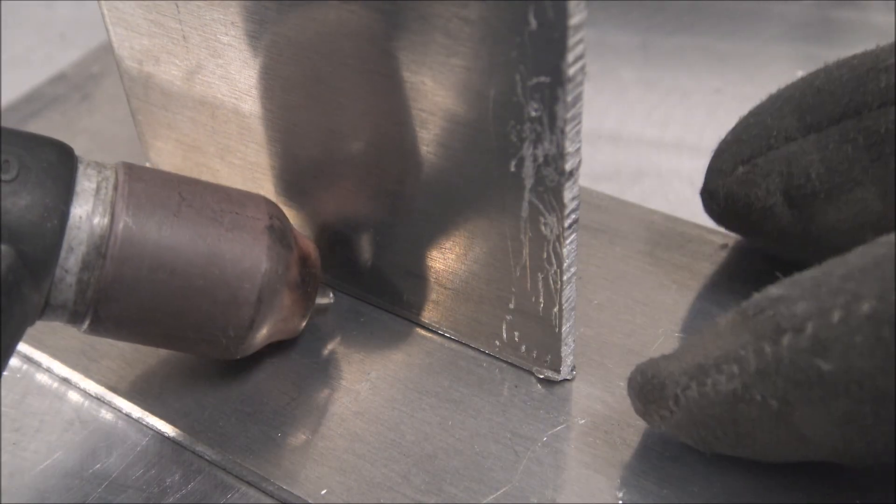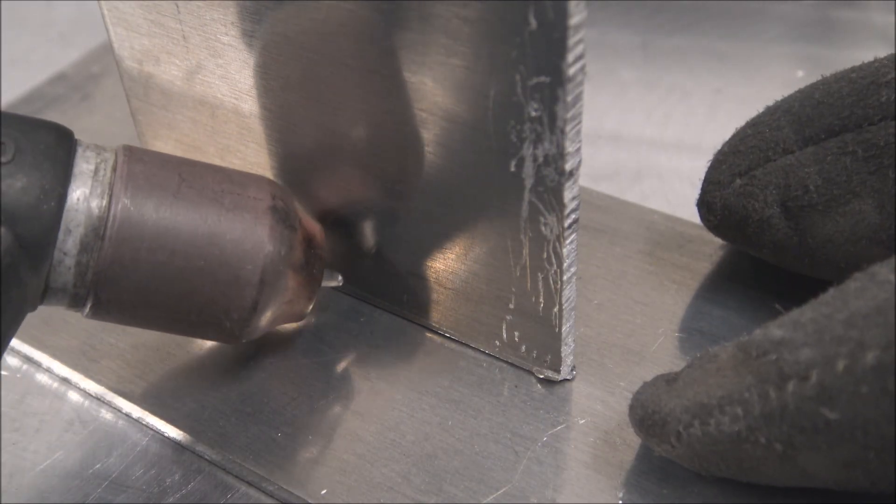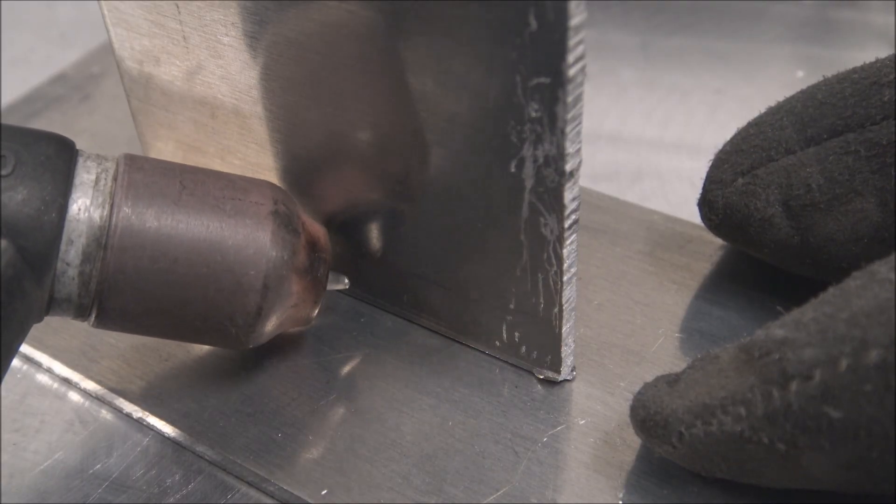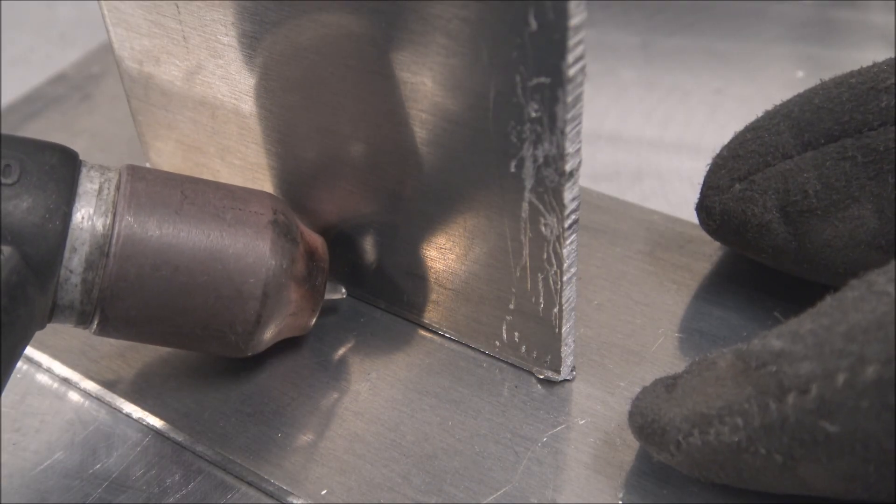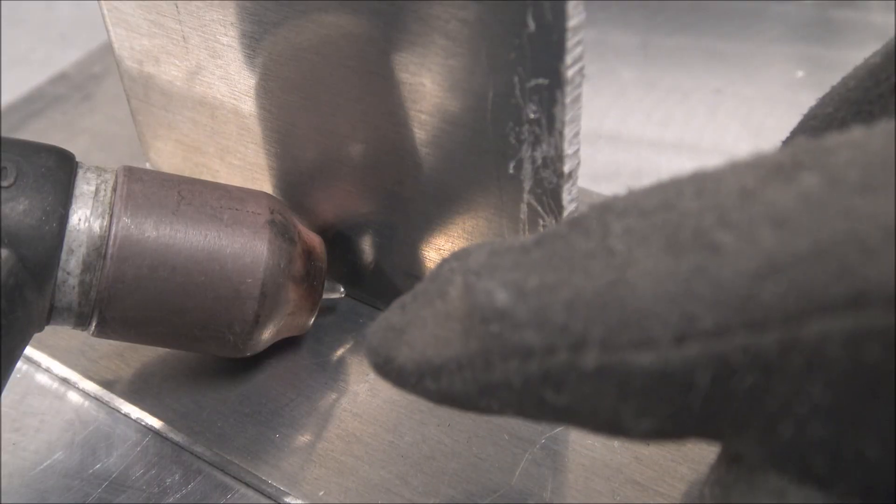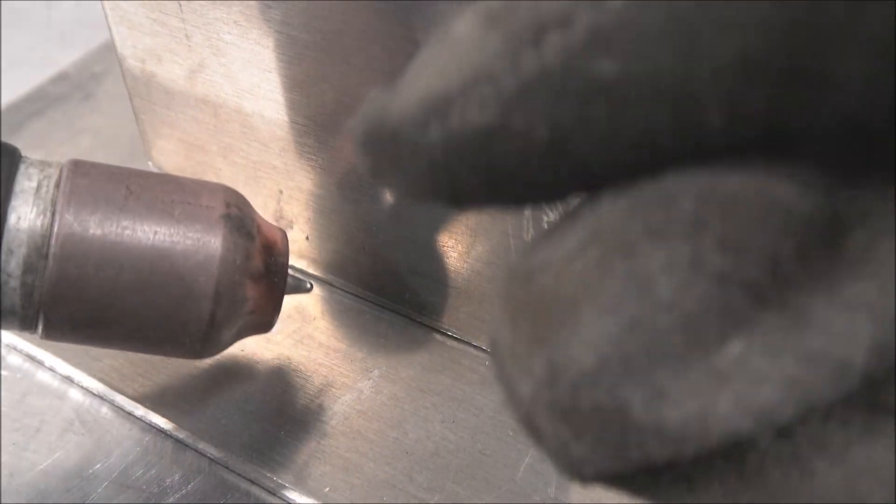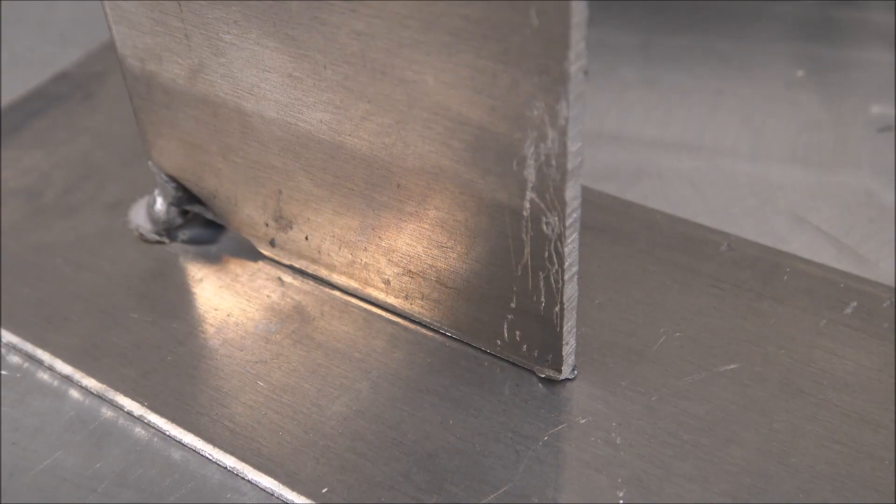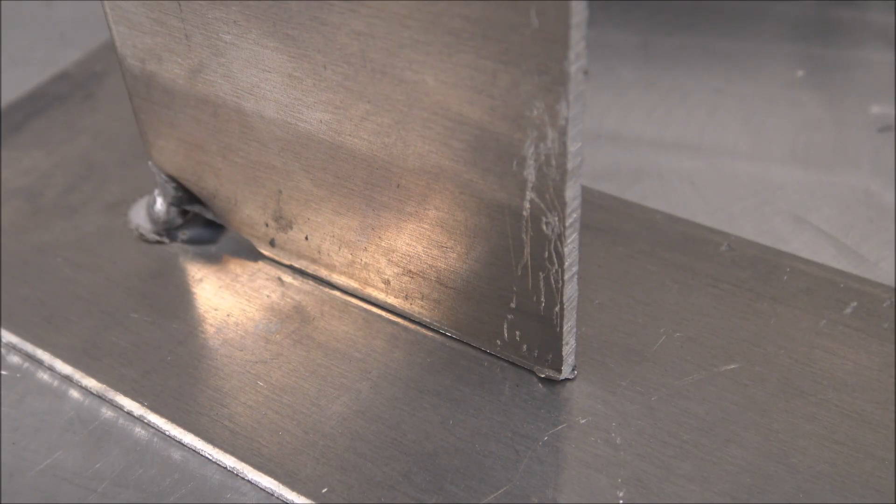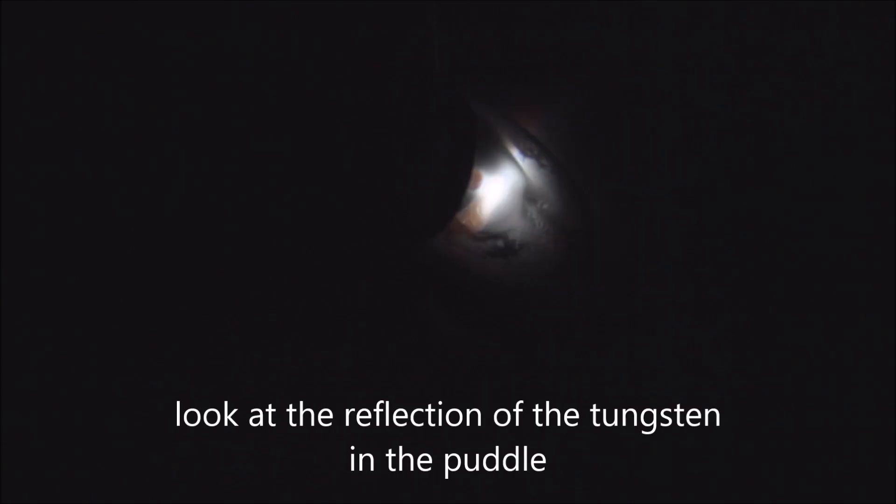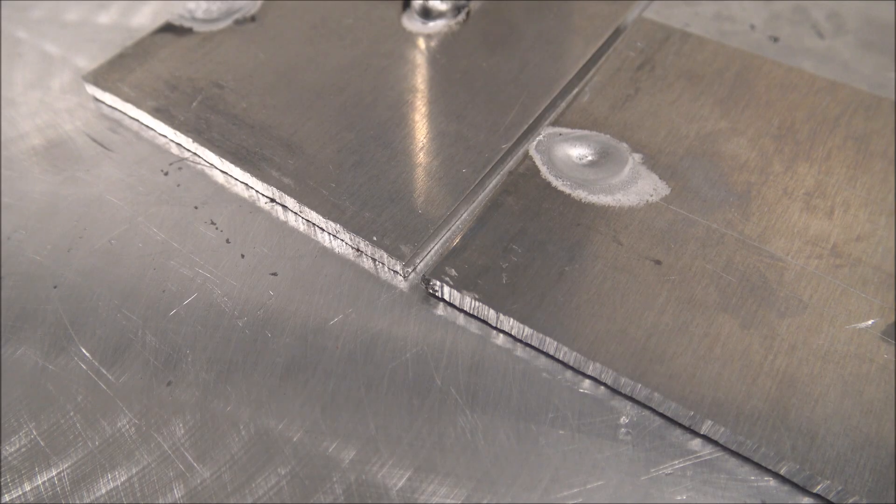This is a T-weld tack out in a hard spot. Like I was talking about earlier, I got my welder set down at 25 Hertz. The lower the Hertz, the more the puddles shake around. That agitation will make them more likely to shake together and touch each other. Like I said though, I don't use this technique really, but kind of interesting to talk about. See how much that puddle is shaking around?